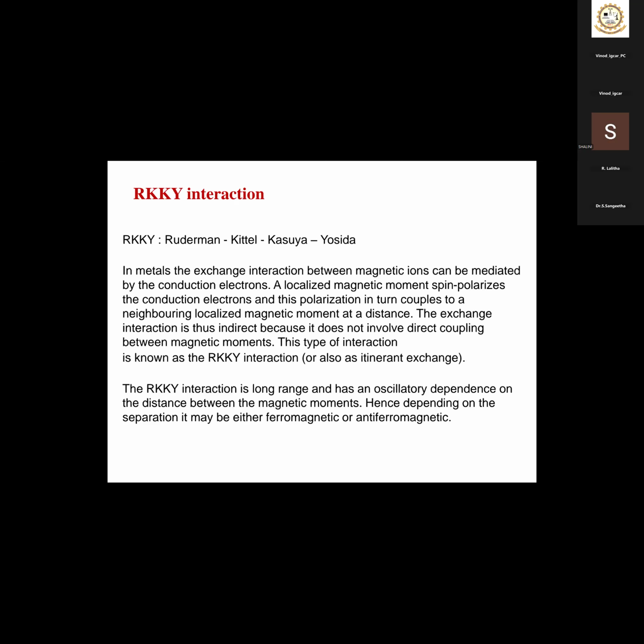But we studied this because we had earlier experience with the europium selenide, EuSe, which I have not shown, that showed some metamagnetism. Metamagnetism means that in some antiferromagnets, when you apply a field, it can flip the spin. Antiferromagnets generally have opposite moments, but in some antiferromagnets at high field, the opposite spins can flip with the external field. It is called metamagnetism.